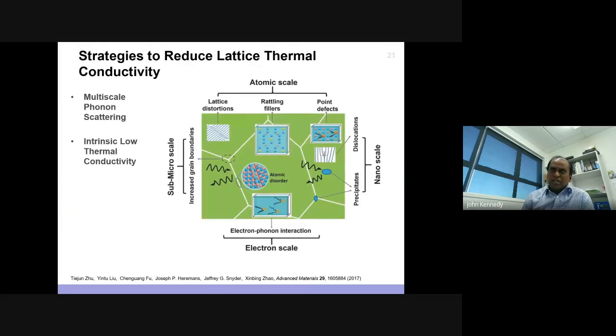So in a nutshell, as I said before, in the early days people worked on looking at the thermal conductivity, looking at the lattice and electron-phonon interactions, at every scale, even atomic scale, nanoscale, sub-micro scale, you name it. It's because lattice thermal conductivity depends on multi-scale phonon scattering, and every material has got intrinsic thermal conductivity. So when you do some kind of tuning, either defects or if you create more dislocations, then you obviously can tune the thermal conductivity as well. So this is a kind of overview of what is happening in the rest of the world on this thermoelectric efficiency journey, and what are the complications.